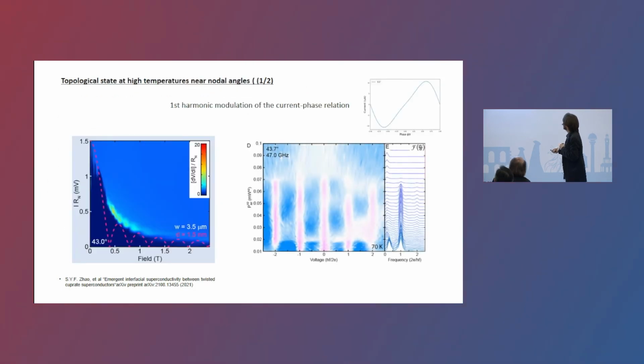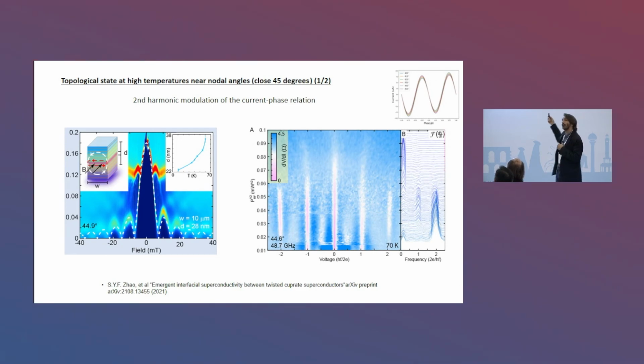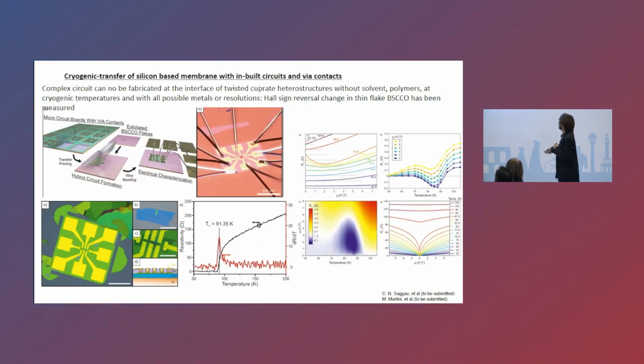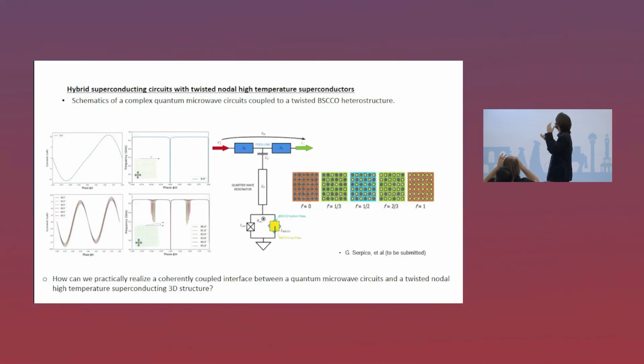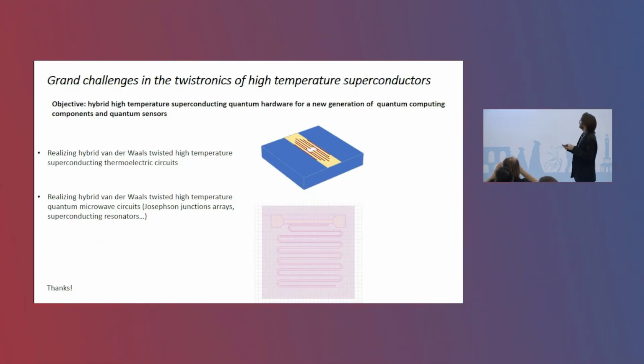What happens is, at a specific angle near 45 degrees, you can see very special states appearing, like fractional Shapiro steps, second harmonic modulation, so a changing current phase relationship. Also asymmetry in the Fraunhofer pattern and fast oscillation, as you can see here. Finally, in order to improve our method, we are now trying to go to a hybrid superconducting system, so we are developing another method in order to combine a very complex circuit. I have to go fast because otherwise I won't finish. But we are working on this. Okay, thank you very much.